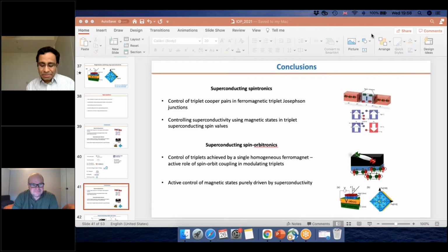Yeah, this is a very interesting question. It is possible, in the sense that if you have a non-magnetic material and you apply a high magnetic field, you do see that one of the spin bands moves up in energy. But the key fact is that the moment you remove the magnetic field, it goes back. The key thing about ferromagnets is that they can maintain this even in the absence of a magnetic field. So it is very difficult to get the same amount of splitting that you have in ferromagnets, and to get the same polarization you would need to apply a very high magnetic field in a normal metal. However, you can use spin orbit coupling. If you have spin orbit coupling in a normal metal, for example platinum, and you pass a charge current, the electron spins get deflected, and the scattering depends on the spin orientation. So you can get a spin current without applying any magnetic field in a non-magnetic metal. So that is possible.